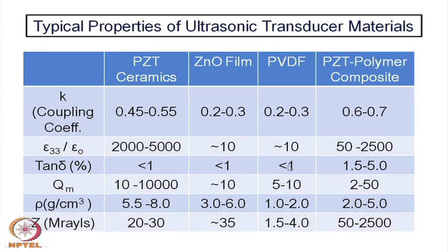there is one variety of polymer, PVDF, the polyvinylidene fluoride. That is also a piezoelectric material, of course, with a relatively low coupling coefficient, and the epsilon prime is also quite low.